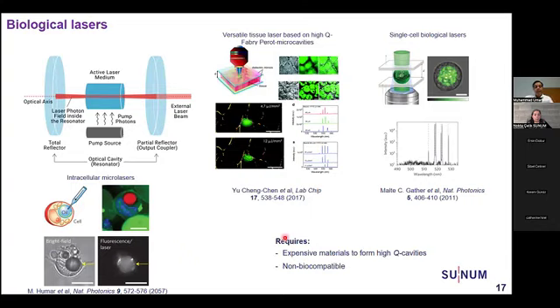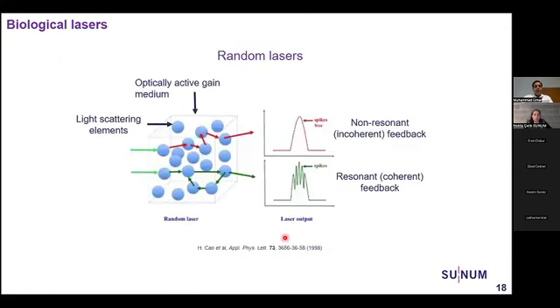So this kind of laser is made from expensive materials, and it requires very high Q cavities. And also these lasers are not biocompatible, so they could not be utilized in living creatures. Therefore, our target was to fabricate a fully biocompatible laser that could be utilized in living systems. So we use the random laser. Basically, the random laser is very easy to fabricate. We put some amount of randomly scattered nanoparticles inside the light emitting solution.